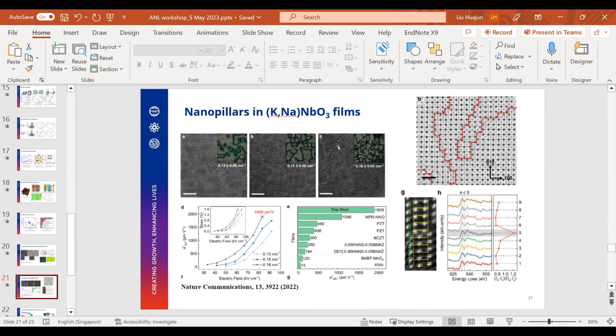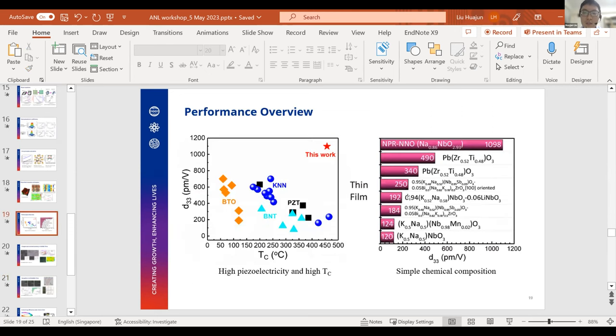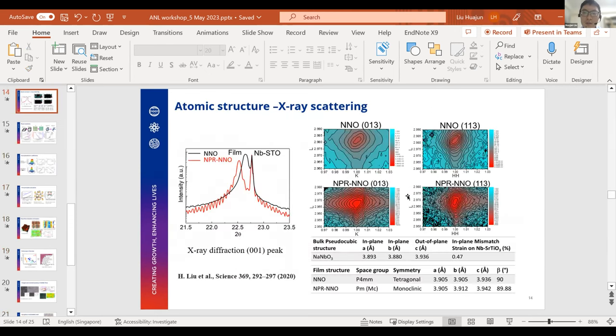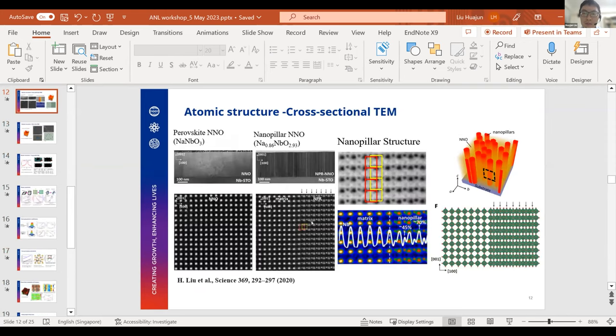Well, it's nice because I guess the interfaces are not full of dislocations, right? That's right. Really clean interface. The lattice is quite coherent, actually. I think it's an amazing part. If you look at the lattice between the matrix and the pillars, they're actually very coherent. There's not much distortion. So that may be one reason why their performance is much better than the other attempts with lead titanium oxide or barium titanium oxide.